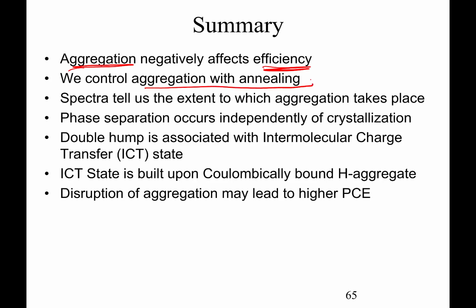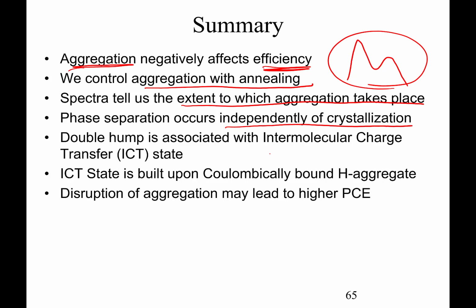The spectra tell us the extent to which the aggregation takes place with that double hump spectrum in here. We see rather the other way around. It's more like this. Phase separation we've recognized, didn't go into too much detail in here, but this occurs independently of crystallization with these materials. That double hump in here is associated with this ICT state. That ICT state, that intermolecular charge transfer state, is built upon coulombically bound H aggregates. This is where the molecules are perhaps a long way apart from each other or slightly at an angle. And we thought that maybe the disruption of this aggregation may lead to higher power conversion efficiency in here.